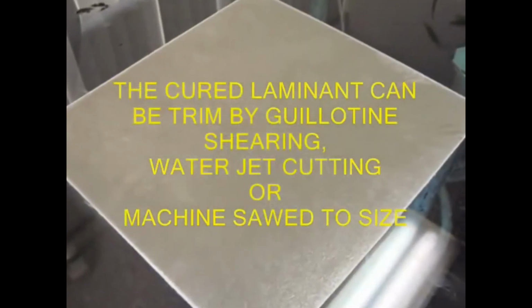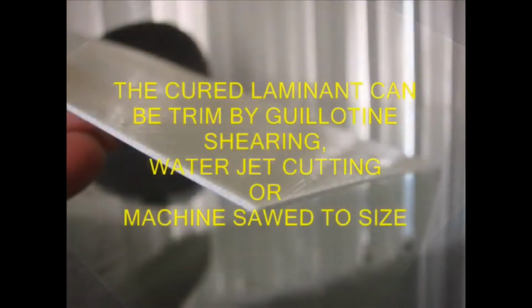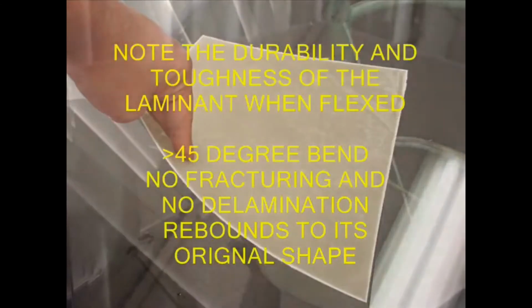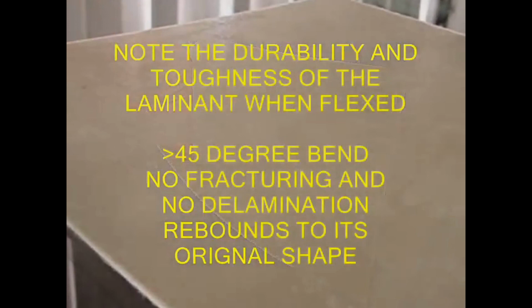The cured laminate can be trimmed by guillotine shearing, water jet cutting or machine saw to size. Note the durability and toughness of the laminate when flexed more than 45-degree bend, no fracturing, and no delamination; it rebounds to its original shape.